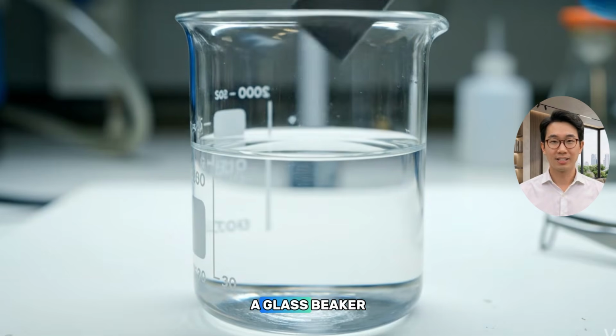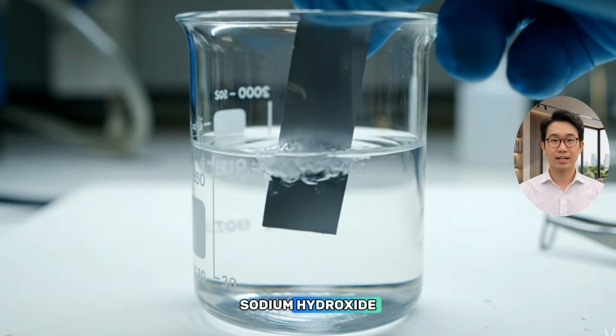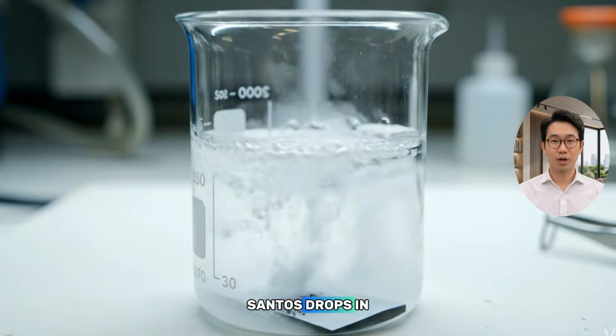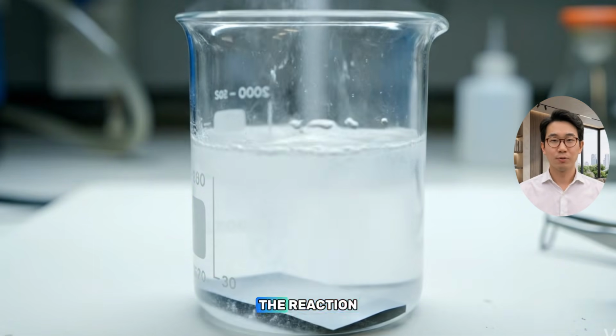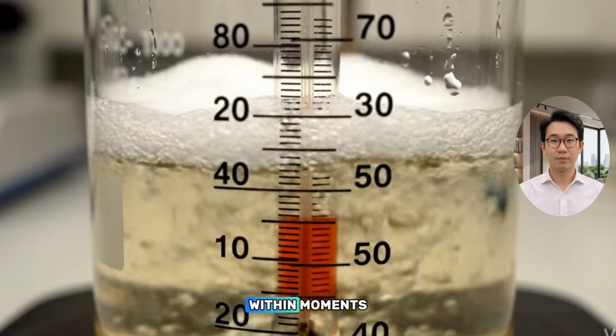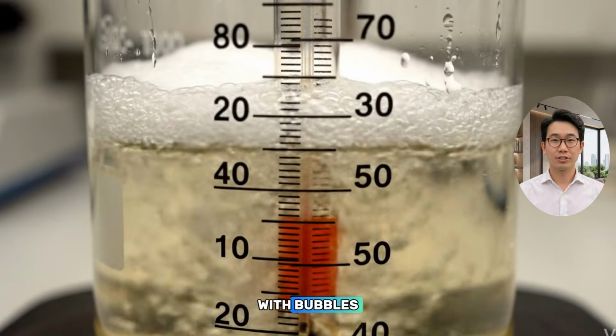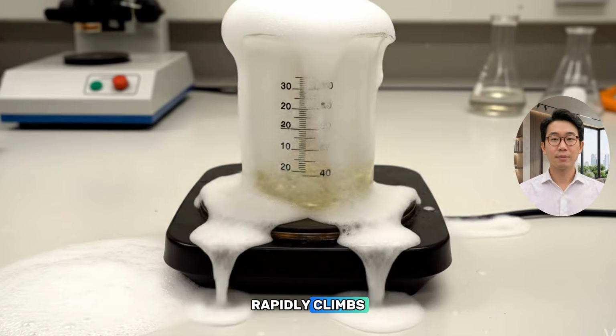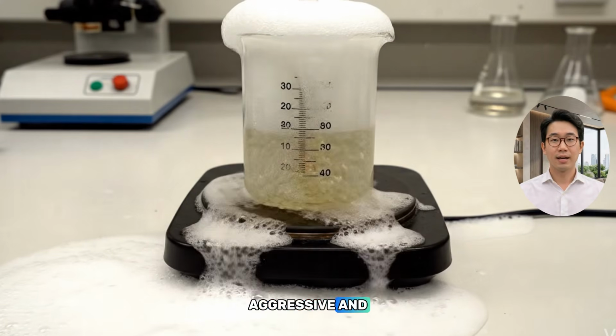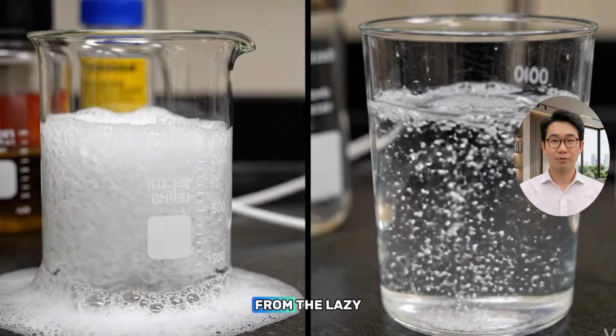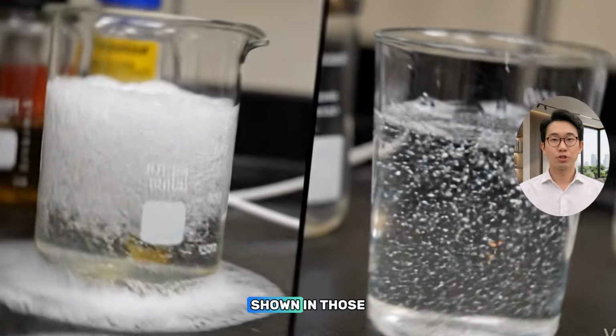Picture a glass beaker filled with a sodium hydroxide solution. When Dr. Santos drops in a fresh strip of clean aluminum, the reaction is immediate and violent. Within moments, the liquid is boiling with bubbles, and the thermometer rapidly climbs. It is loud, aggressive, and unmistakable, a far cry from the lazy fizz or mild warmth shown in those viral